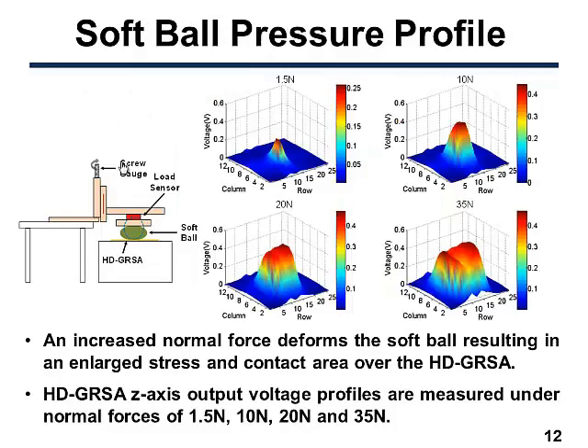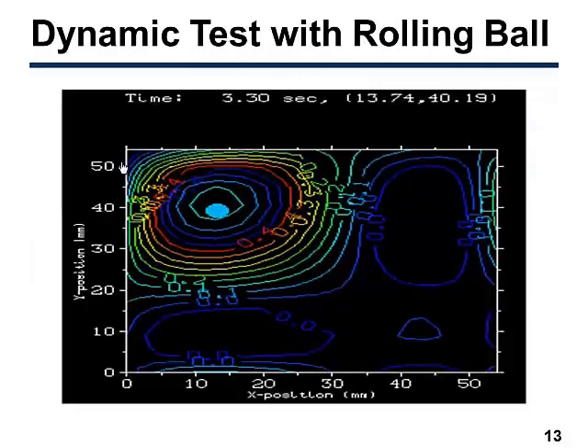After that, the ground reaction sensor array is tested under a soft ball. An increased pressure applied on the soft ball will deform the soft ball and result in an enlarged contact area and contact pressure. For the high-density ground reaction sensor array, the output voltage profile is plotted under applied normal forces of 1.5, 10, 20, and 35 Newton.